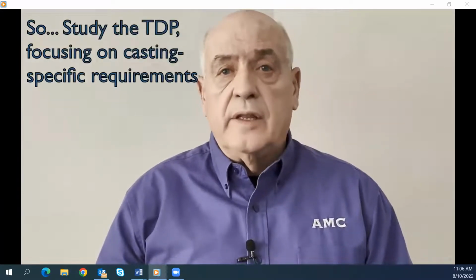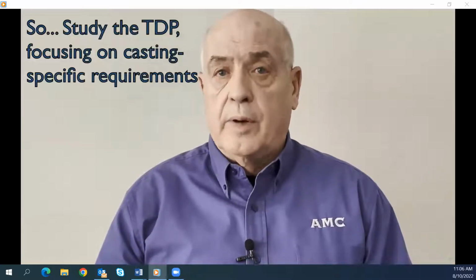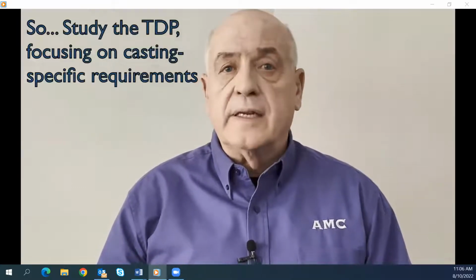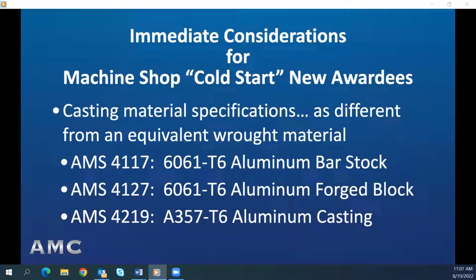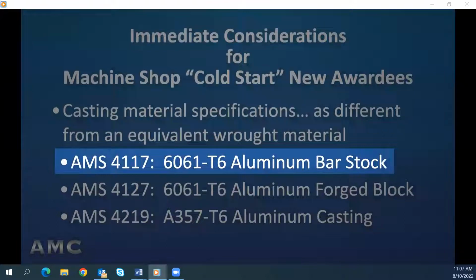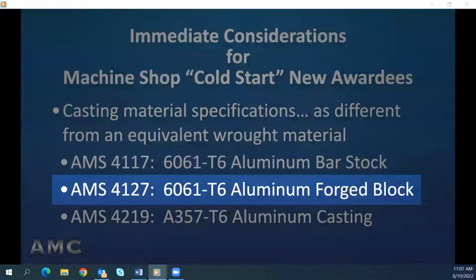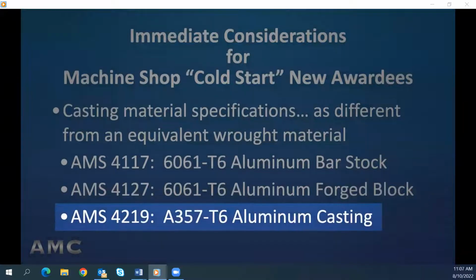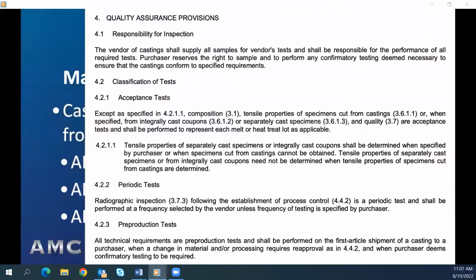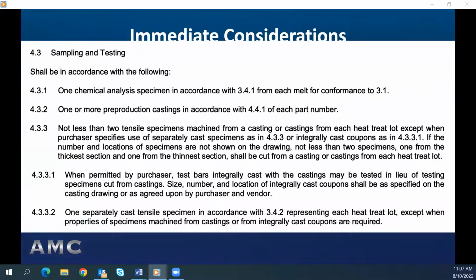a legacy casting contract. Immediately after award, study the technical data package as would be prudent for any component, but focus on the requirements that are casting specific, such as the material specification, which for a casting will be different and more complex than for an equivalent wrought metal specification. For example, here are the AMS Section 4 quality assurance provisions for machined from bar stock 6061 aluminum, for machined from forged block 6061 aluminum, which is more extensive because of grain alignment, and the comparable A357 cast aluminum. Section 4 is far more extensive for the cast aluminum.